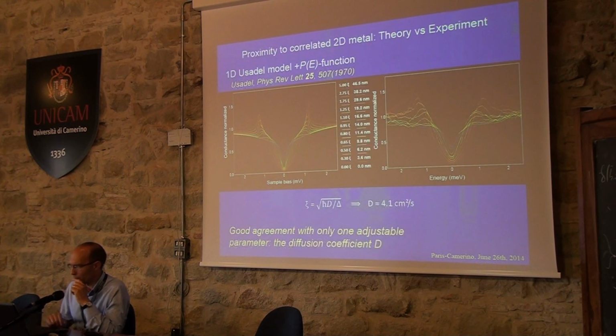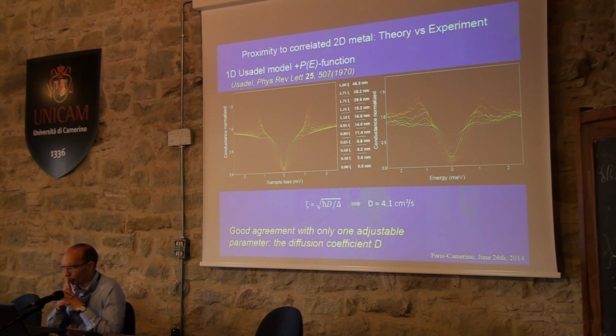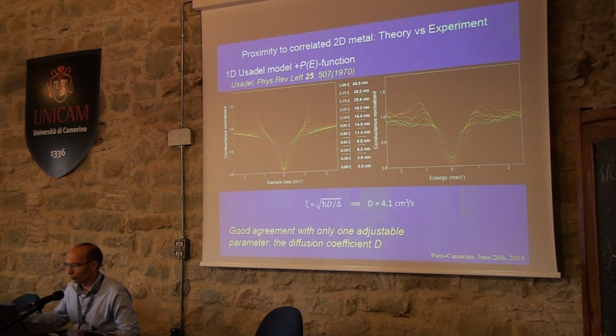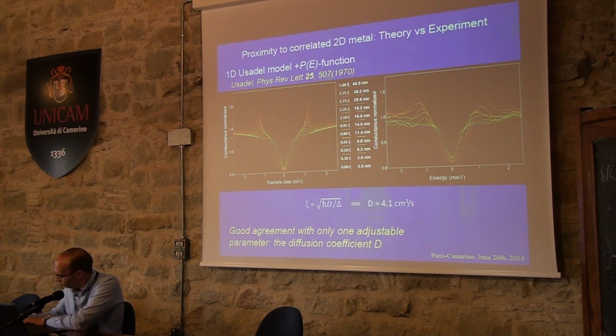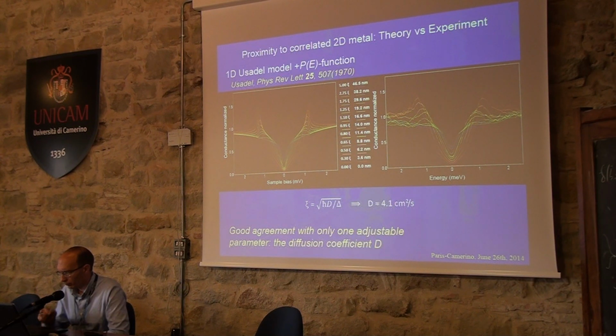And again, next slide. In this way, by implementing this formalism, taking into account both the proximity effect within Usadel formalism and the Altshuler-Aronov effect within this PE function approximation, we were able to generate on the left plot theoretical curves of the evolution of proximity spectra, which are very nicely reproducing the experimental data on the right plot. And all this with only one single parameter, which is related to the diffusion coefficient, which is drawn just below the point.